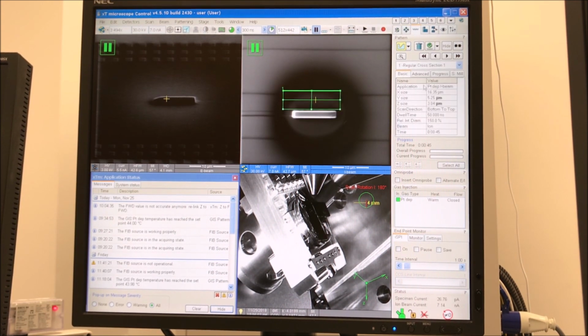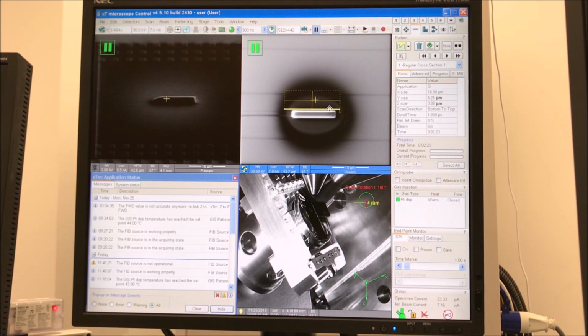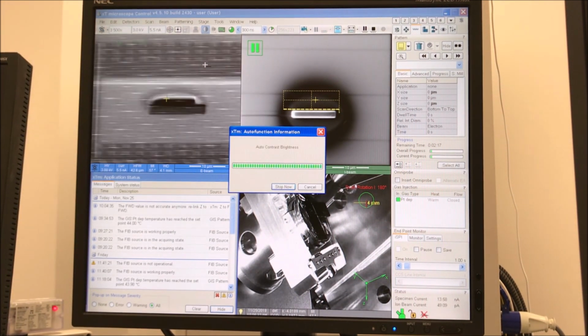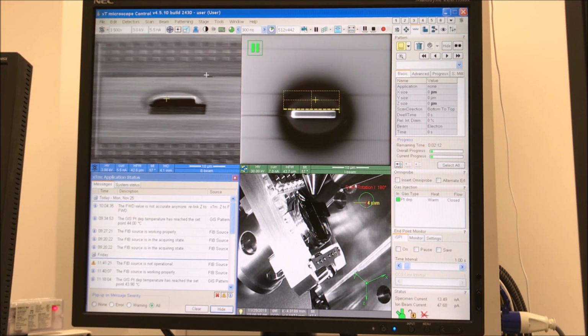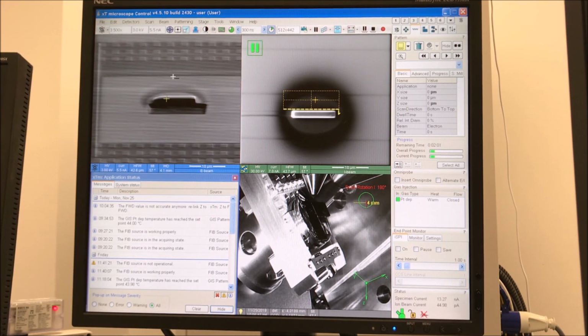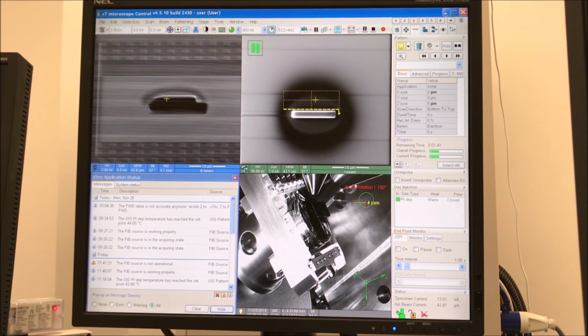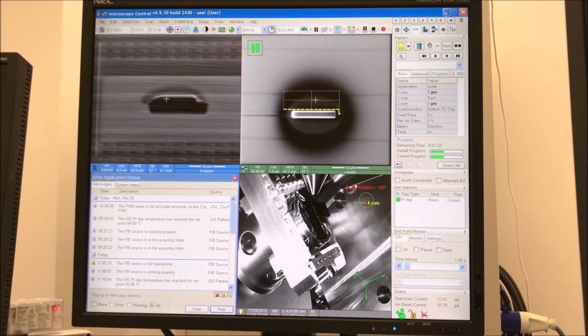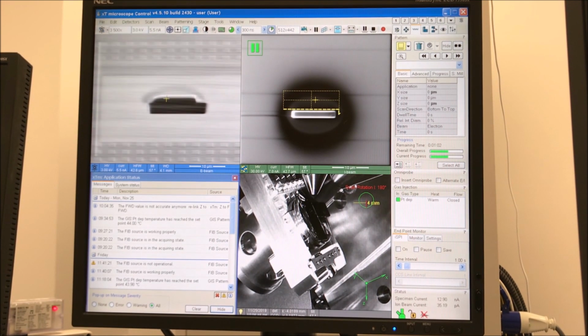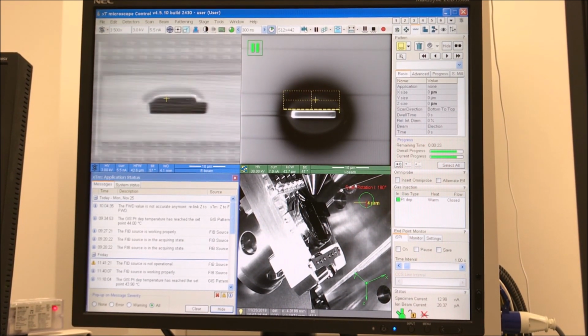So for this, I'm going to use the regular cross-section with a rotation of 180 degrees, which you can do in the Advanced tab. And so you want to use silicon for your application file. That's the general milling file. I think the X and Y dimensions for this were 16 and 5, and then the Z was 3, but really in silicon it ends up cutting more like about 7 or 8 when you input 3, so it's a little bit skewed.